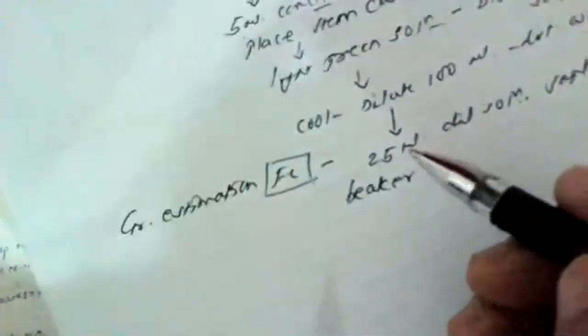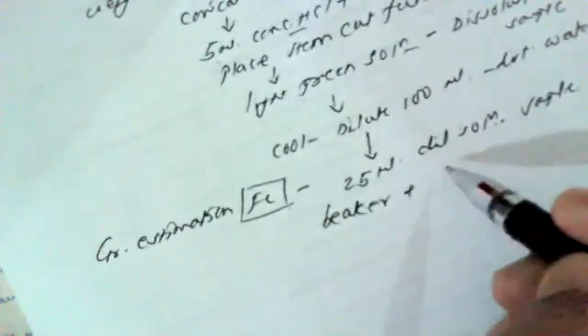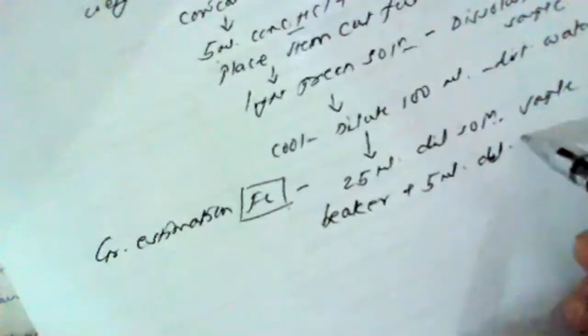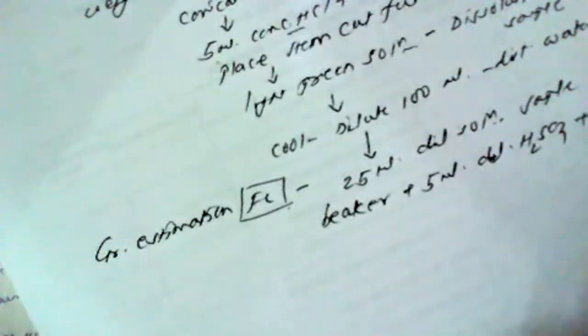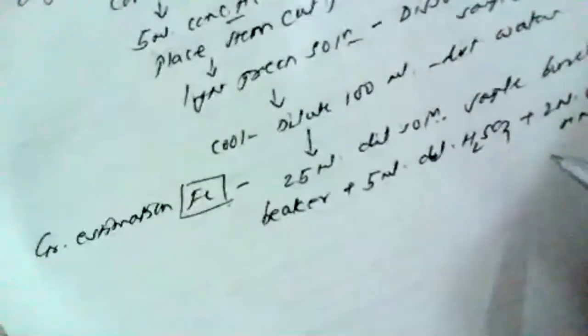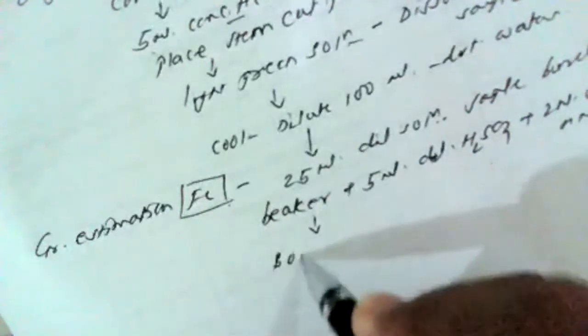First of all, we have to estimate the iron content from this razor blade, by using gravimetric estimation of iron. So first of all, we have to estimate iron gravimetrically. For this, first of all, we have to take 25 ml of this diluted solution of sample by using a burette. This solution is to be taken in a beaker, 250 ml beaker preferably. Then to this beaker, we have to add 5 ml of dilute sulfuric acid, that is a table reagent, and about 2 ml concentrated nitric acid, that is HNO3.